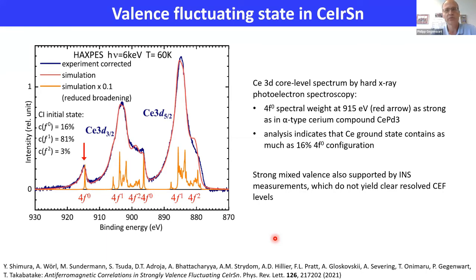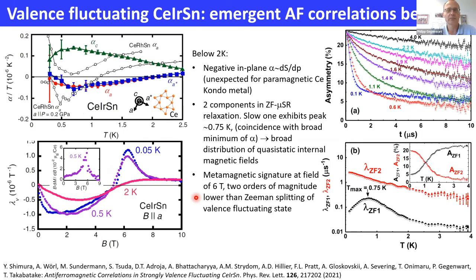But here, according to spectroscopy, we really have a very strong valence fluctuating behavior. So we have as much as 16% 4f0 configuration we see at 60 Kelvin in the synchrotron spectroscopy experiment. So that's a material which is deep in the valence fluctuating regime. And so it was really very surprising for us to observe that when we did thermal expansion experiments, the thermal expansion coefficient in this material upon cooling actually gets negative at low temperatures.